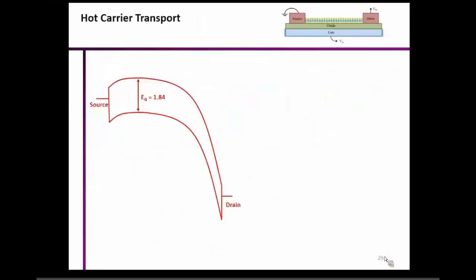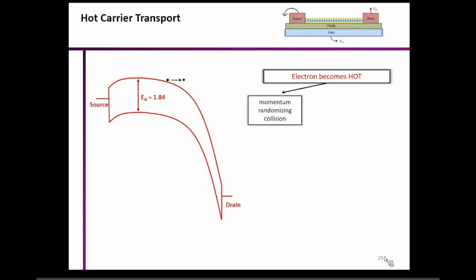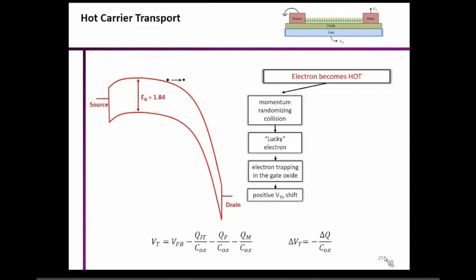And this is what we call hot carrier transport. So when we apply a large drain bias, you create an extremely large electric field at the drain end. And what really happens for an electron which is nearing this drain edge, it will gain a lot of energy from that field. And when it gains a lot of energy, it actually becomes hot. Right? Now once the electron becomes hot, it can go through several processes. One of the processes is that it will collide with another electron, where it will not lose its energy, but its momentum will get randomized. Now once its momentum gets randomized, it can become a lucky electron, and it can get injected into the oxide and get trapped inside the oxide, and that will lead to a positive threshold voltage shift.